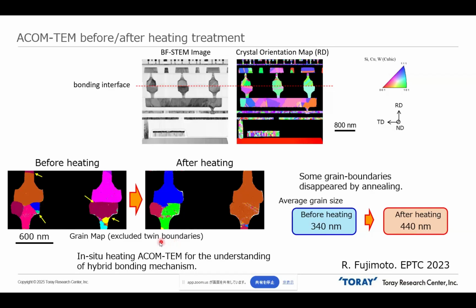So I believe this technique, in-situ heating TEM combined with ACOM TEM, is a very useful technique to understand the hybrid bonding mechanism. So we would like to propose this technique to know the mechanism of copper-copper hybrid bonding.